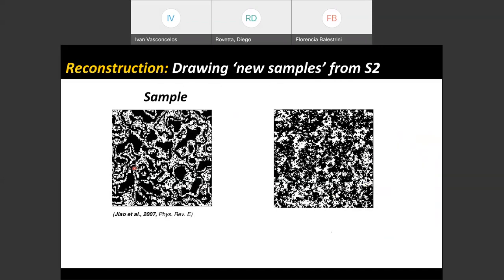So here you see the sample, and the sample comes from a laser speckle pattern pointed at a specific microheterogeneous material. You can see right away that there are at least two scales of correlation in this material, because you can see the big black blobs and they correlate spatially with each other. You can also see that there are these black lines that have orientations and correlate with each other. So there's at least two scales here.